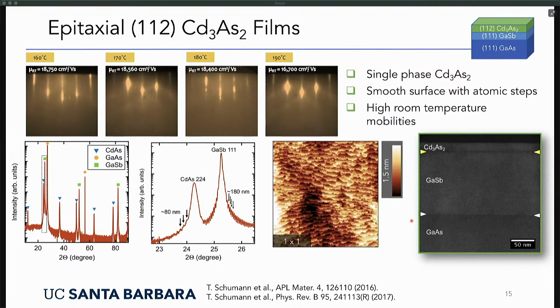In this case, the heterostructure was a gallium arsenide substrate, a gallium antimonide buffer layer, and then cadmium arsenide. What is also encouraging is that these are room temperature mobilities for these different growth temperatures. They're close to 20,000, so this is quite a high mobility. So this was encouraging for the 112.